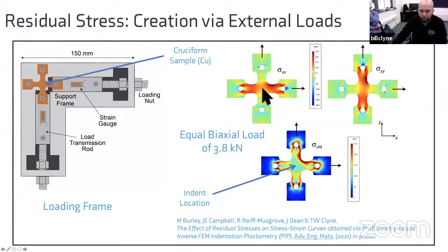Now, this leads to the von Mises stress looking not quite as uniform as you might expect initially, but it does result in this central region here having a relatively constant residual stress. So we're looking at the equal biaxial case, and in this region, the von Mises and indeed the X and Y components of that are relatively constant.